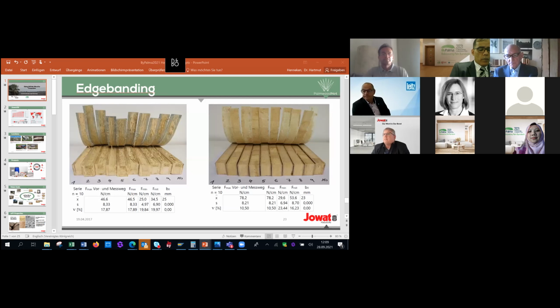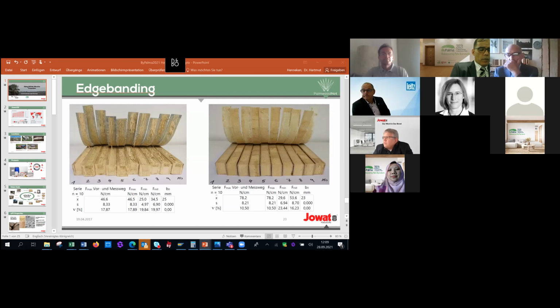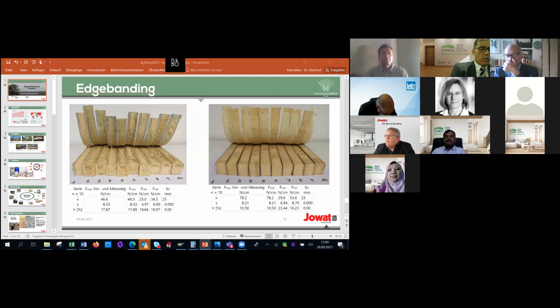Here you see pictures. Actually, these are two pictures, two sets with the polyurethane hot melt. You can see here you have a strength of almost 80 Newton per centimeter if the arrangement is perpendicular. So you're gluing the end grain, actually. You're gluing on the cross section of the vascular bundles. So you have higher forces here. Here you have much more fiber, but it's okay, but it's much lower forces associated with this.